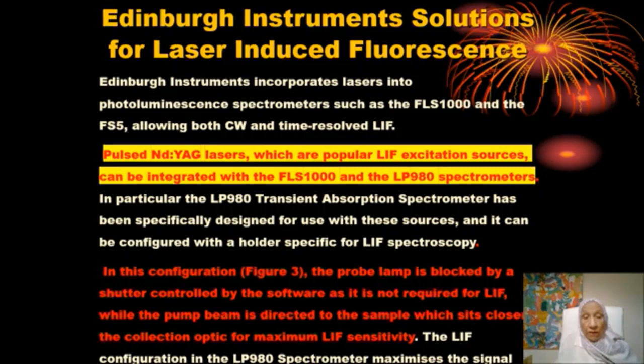In this configuration, as figure 3 will show, the probe lamp is blocked by a shutter controlled by software, as it is not required for laser-induced fluorescence, while the pump beam is directed to the sample, which sits closely to the collection optics for the maximum laser-induced fluorescence sensitivity. The laser-induced fluorescence configuration in the LP-980 spectrometer maximizes the signal.